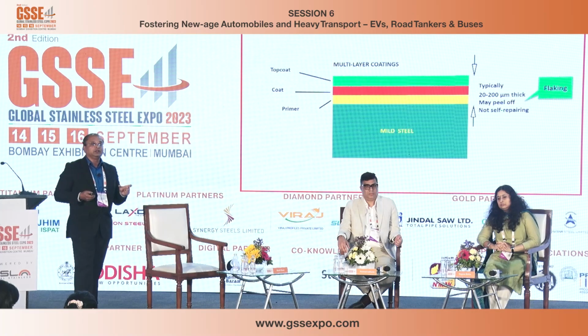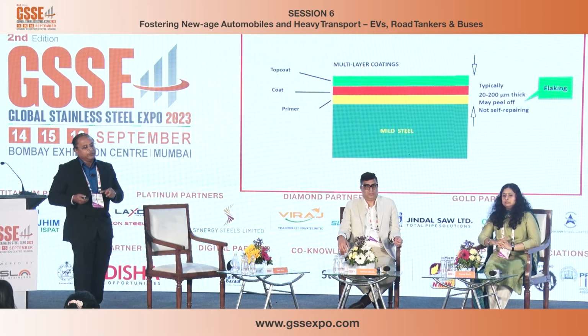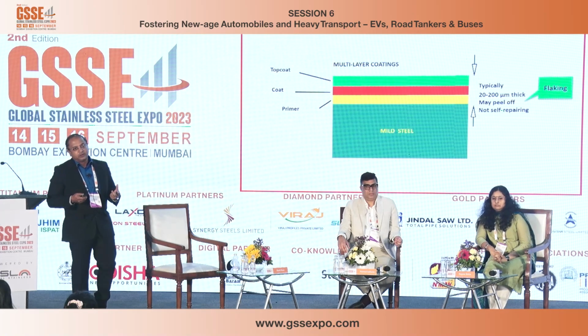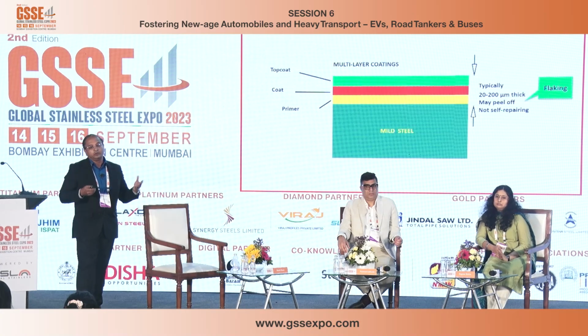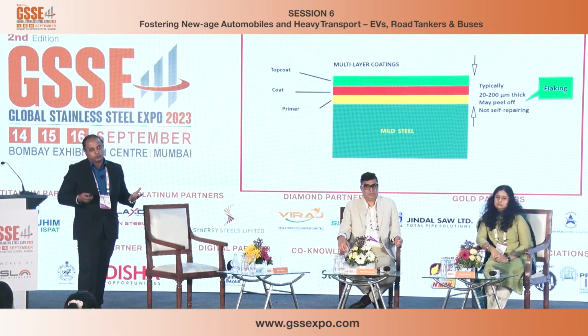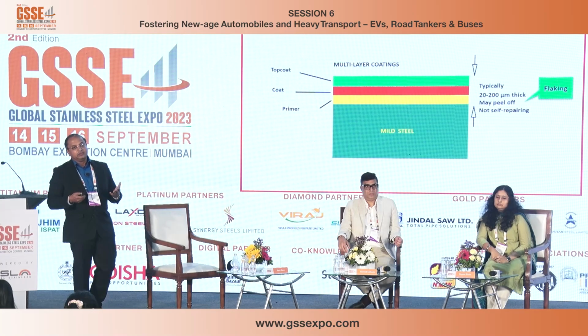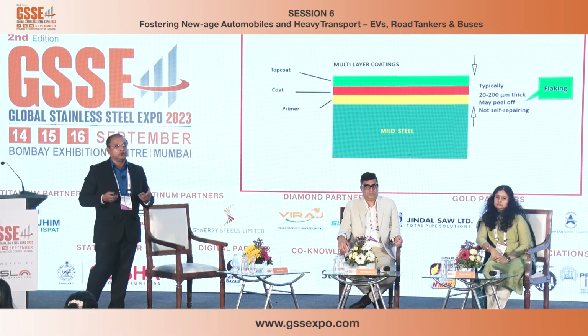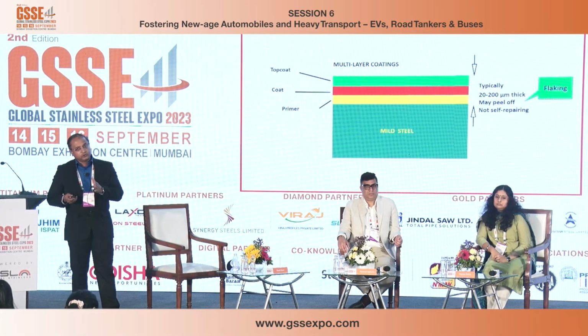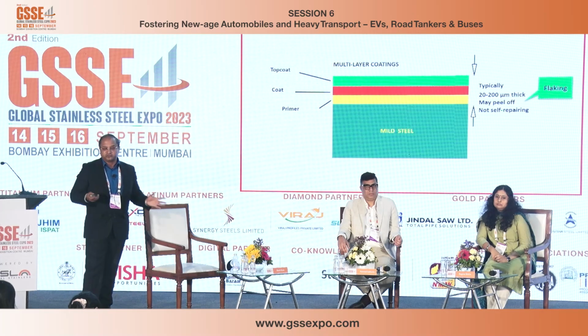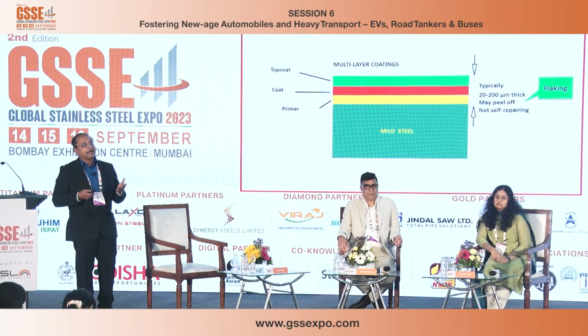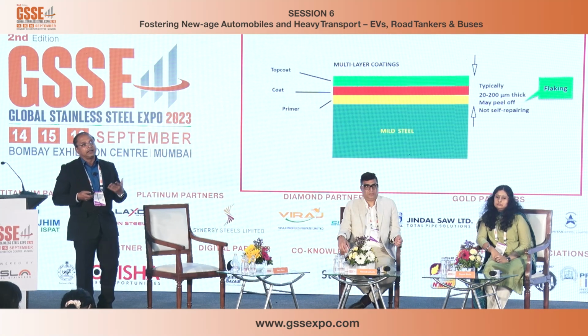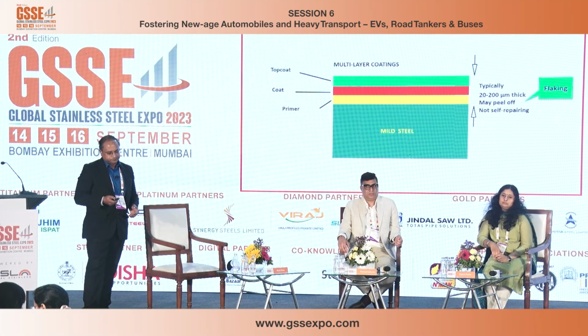And this phenomenon is known as flaking. From the areas where flaking happens, immediately the chlorides in the atmosphere start attacking the carbon steel substrate and corrosion starts. Once the corrosion starts, it's almost impossible to stop that. So this is where the difference of stainless steel lies, as compared to a galvanized or a painted material.